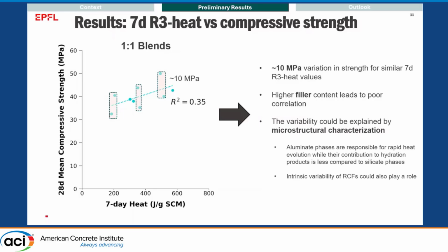I think this variability could be explained by microstructural characterization, which I plan to do in the future. But I have a small hypothesis, inspired from the literature too, that aluminate phases are responsible for rapid heat evolution. So in the R3 heat, it could be that more aluminate phase formation can lead to a higher heat signal, but the contribution to the strength might be lesser. So this needs to be validated with microstructural characterization.